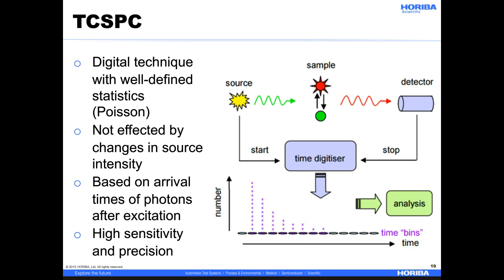Since TCSPC is based on the arrival times of photons after excitation, the results are not affected by changes in the source intensity. In other lifetime techniques, fluctuations in the source may have an effect on the result and therefore the final analysis. In addition, TCSPC offers very high sensitivity and precision with resolvable lifetimes in the picosecond range.